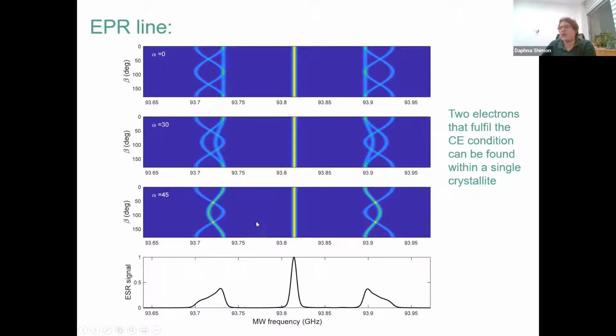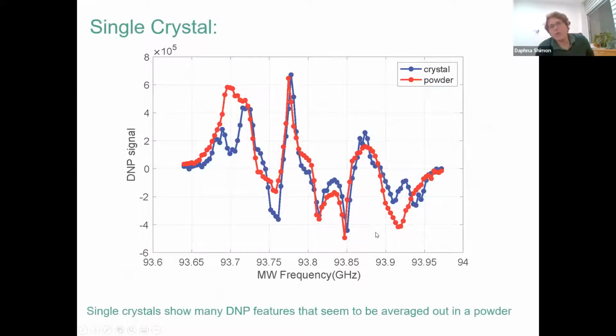And so the last thing that we're doing now, and this is just some preliminary results, is we're looking at single crystals with DNP. And the goal here is to really understand the mechanism that's giving us these large enhancements on the side. And you can see in blue, the single crystal, there's a lot more features happening, even more than in the powder. And so I think that once we are able to really look at the single crystal as a function of orientation and really see what's happening, it'll help us understand what's happening in the powder also. But right now, our guess is that it's a truncated cross effect.